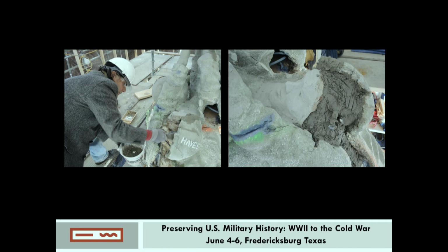For rebuilding, the rebar were first encased in Planitop, which is a polymer modified repair mortar that has an added corrosion inhibitor. So anything right around the rebar was molded around that area first. And then the voids were filled with a concrete mixture consisting of 1 part type N cement, 3 parts sand, and 3 parts pea gravel. The concrete was either poured into the voids formed by the reattached fragments or built up in several lifts.